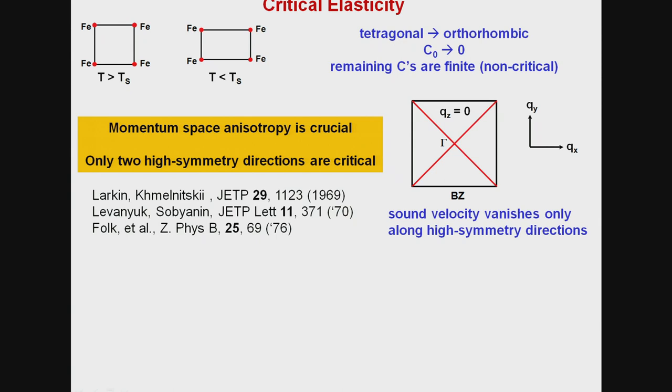So, if you excite phonons along any other lines, or along any generic polarization, then you will not notice that there is a second order phase transition going on, because the phonon velocity is going to remain finite. So, in other words, momentum space anisotropy is very crucial in order to feel this criticality. And it is restricted only to these high symmetry directions.